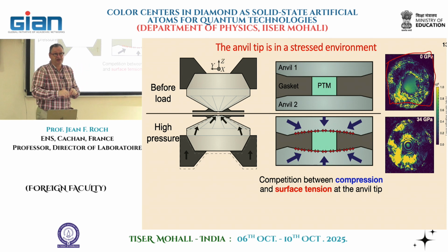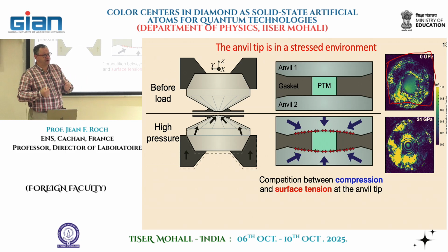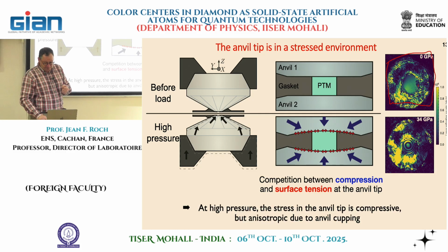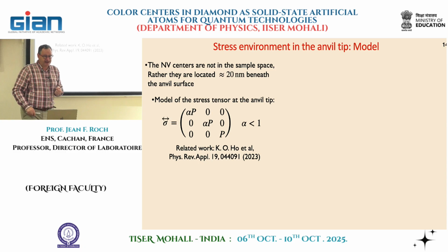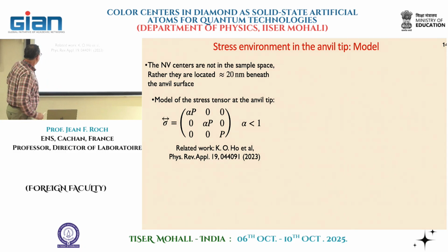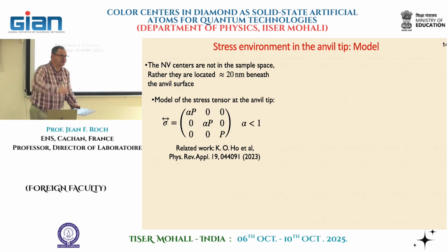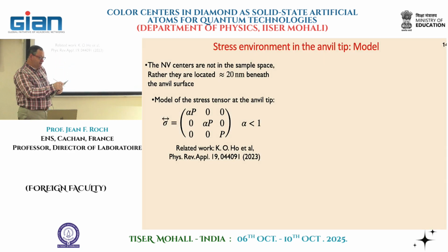Since we have the NV centers right above the tip, at the surface of the tip they will have a strong stress that is not applied along their axis. So the NV center is in an environment which is non-hydrostatic. That's what we think. We can model this effect by applying a quite simple stress tensor at the anvil tip. In the Z direction, there is a pressure applied, and in the transverse direction, due to the cupping, it is reduced by a parameter alpha, due to the surface tension. And alpha should be below 1.